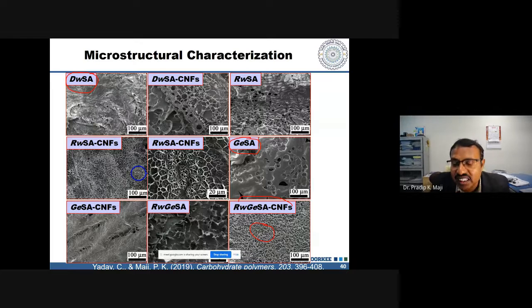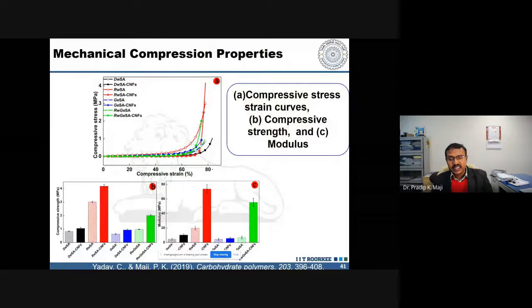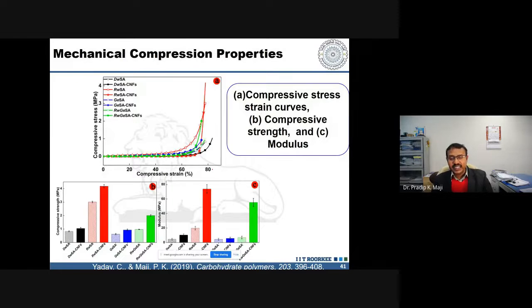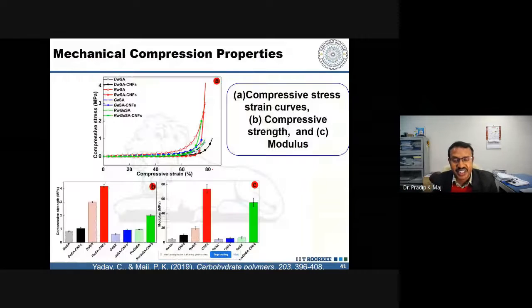This structure is very important because a good morphological structure gives very good dimensional stability. We are most interested in the rice water, alginate, and CNF combination because it may give better properties due to its honeycomb-like structure. This honeycomb structure forms because calcium ions act as a chelating agent, pulling the material close together in different directions.